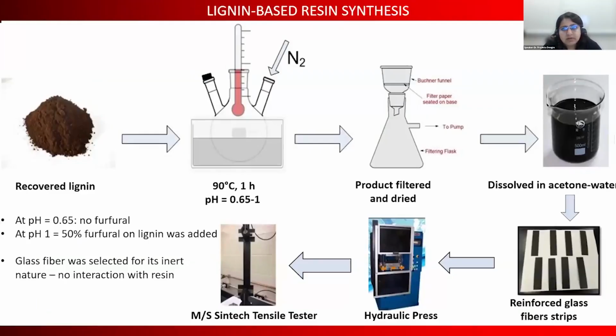So this slide shows the synthesis method of how the resin was made. We took the lignin from the hot water extraction process and subjected it to acid hydrolysis at 90 degrees C for about an hour. The pH ranged from 0.65 to 1. At pH 0.65, there was no furfural added. However, at pH 1, furfural was added. So we tested the effect of the in situ furfural that would be present versus adding furfural ex situ, or externally.